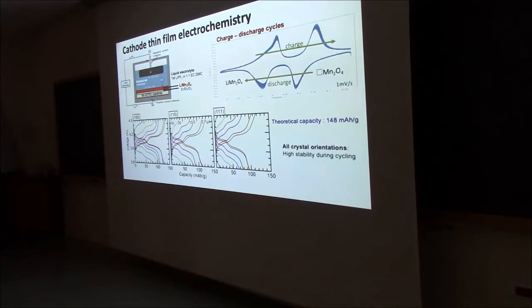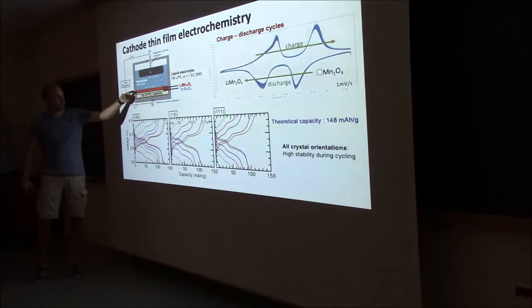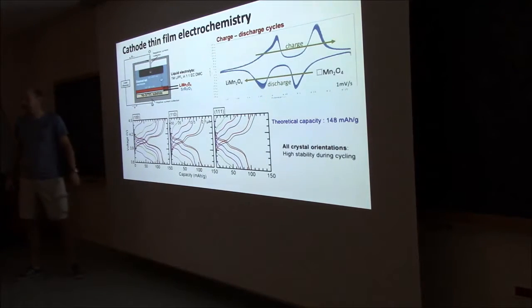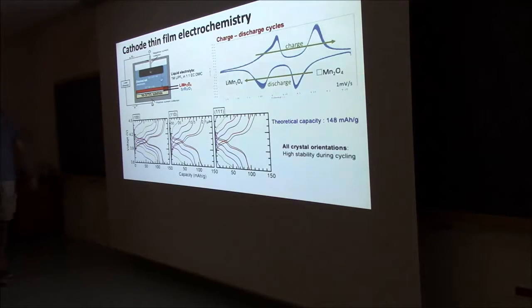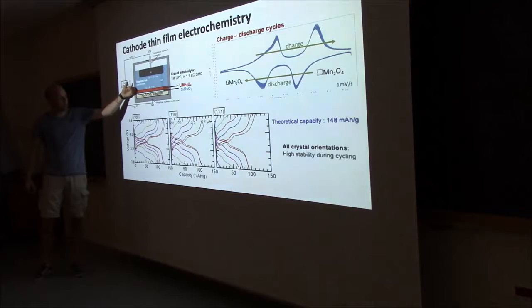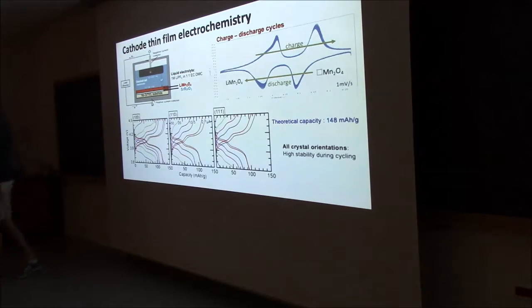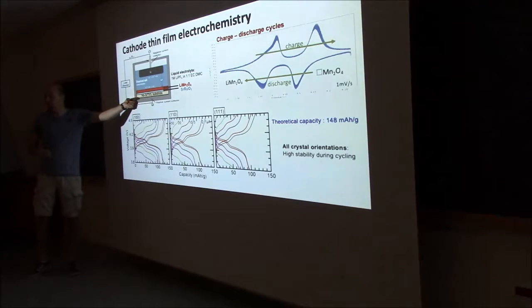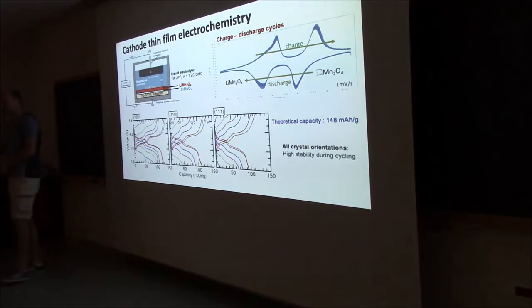Can you describe again why you put in the strontium layer and how that affects? So, what you want is to get the electrons out in the end. This is what should work as a battery. The thing that we're investigating now is we know that with this one directly on the substrate, you have a problem in the band alignments, so you're not able to get the electrons out. It was already published that with strontium germanate you could do that. Then at least you could have it working as a battery, but we're checking now what the difference is. At the same time, we're also using other conducting oxides like lanthanum nickelate and some others to have the same effect, to see how much that improves. For this material we need to do it. There are other materials on the anode side which don't require this extra layer, because there is no problem with band alignment.